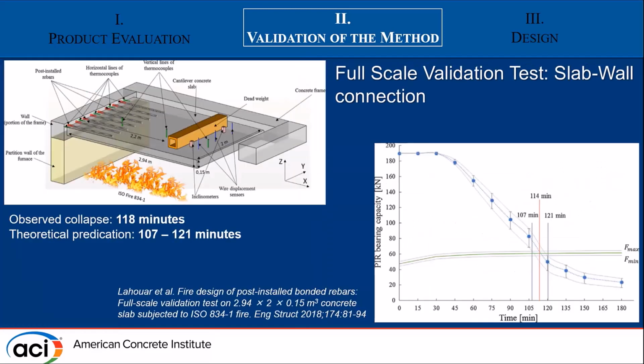The second test was done a few years later and was on a structure which was a slab connected to a wall using 8 post-install rebars. The goal of this test was to see if there was stress redistribution between the rebars during collapse. Here again, there's a good accordance between the calculated predicted failure time and the observed time. We had collapse after 118 minutes, and the predicted failure time was around 2 hours. Both of these tests have been published in the Journal of Engineering Structures, in addition to other validation tests. So this allowed us to validate the resistance integration method, which was the first step before determining a design concept.